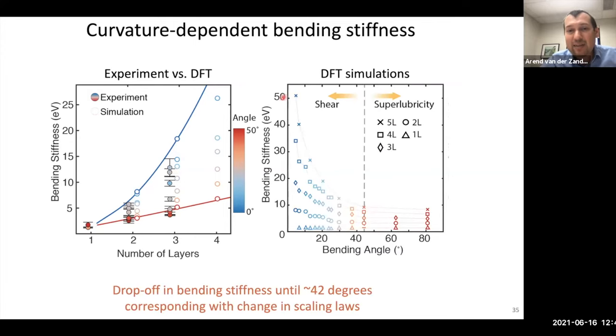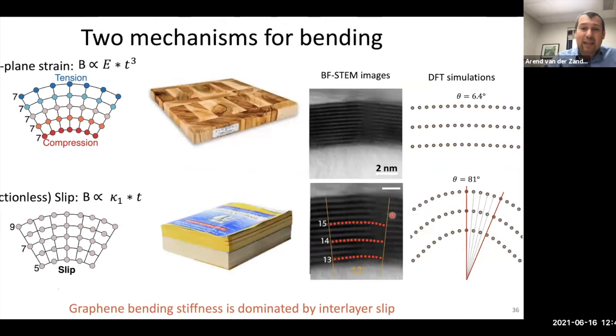Once we had this idea, we could actually use simulations to actually prove it. So here we have a simulation of the stiffness versus the bending angle for monolayer, two-layer, three-layer, four-layer, five-layer. What you see is for small bending angles, the mechanics are dominated by shear where the layers interact and it goes up really quickly. At large bending angles, it's as the layers can slip past each other perfectly freely and everything flattens out. And so basically, again, what this tells us is that the mechanics of graphene are much more like the mechanics of a stack of papers than a piece of wood.